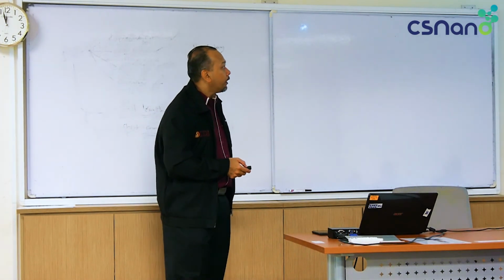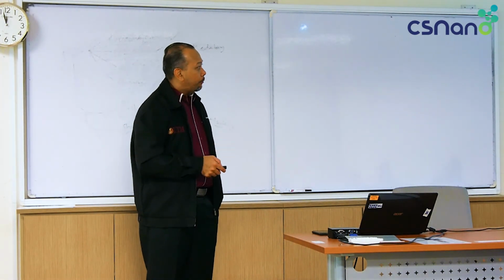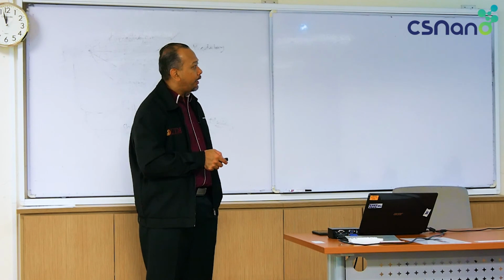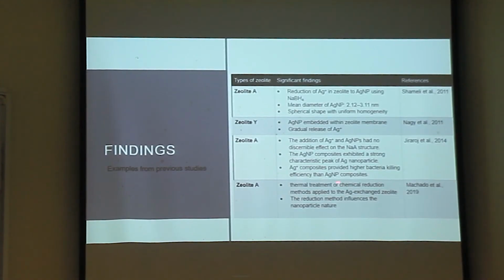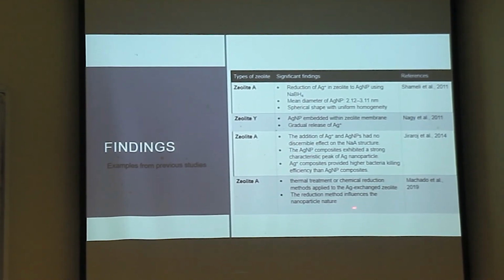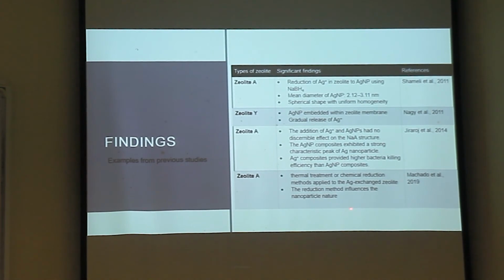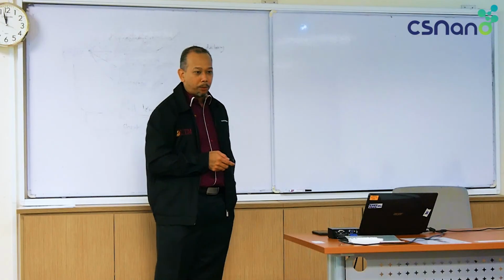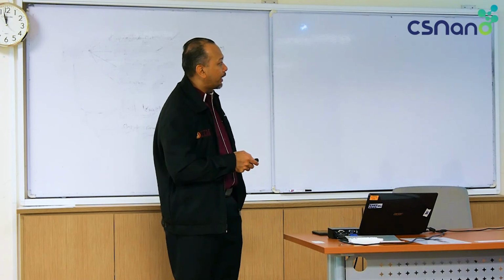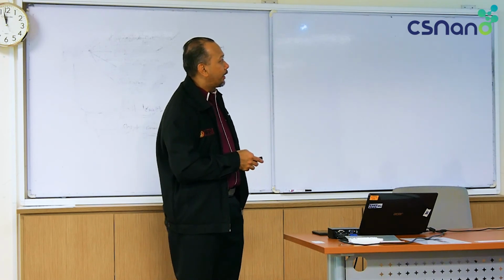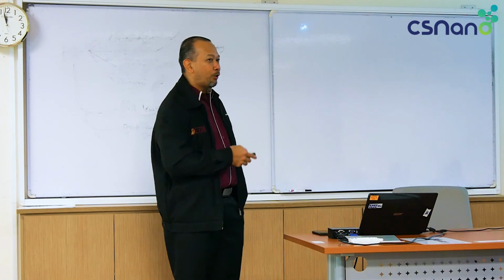Most of the papers here enrich the zeolite structure with Ag+, and after that they reduce it to silver zero, silver nanoparticles, using chemical reduction or, in some cases, heat treatment. So I go to the summary.